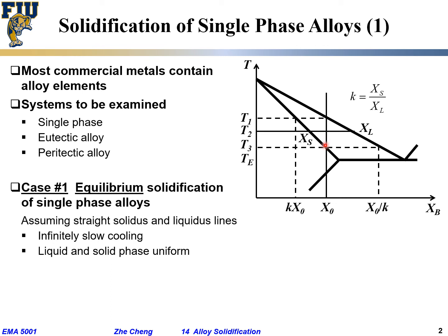When I'm going through the two-phase region, I should have pretty much all solid and very little liquid. When I'm very close to the solidus at T3, my solid composition is x0 and my liquid composition — given by the tie line intercept — is x0 divided by k. So going from top to bottom: all liquid, almost all liquid with very little solid, roughly half-half, very little liquid, and finally all uniform solid alpha.